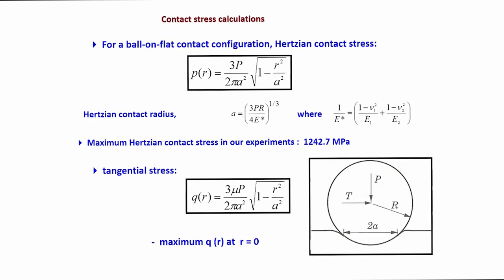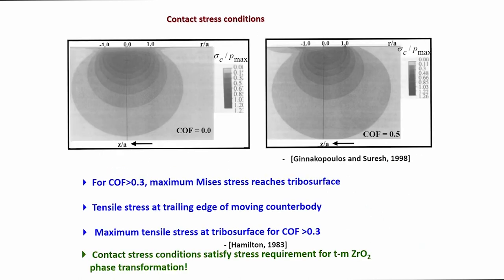One can explain or rationalize this formation of the microcracking by calculating the Hertzian contact stress. You have seen this formula before, but to repeat, p_max is the Hertzian contact stress, P is the load, R is any given radius, and a is your contact dimension, a = (3PR/4E*)^(1/3). Accordingly, the tangential stress can be calculated as q(r) = 3μP divided by 2πa², square root of 1 minus r²/a².